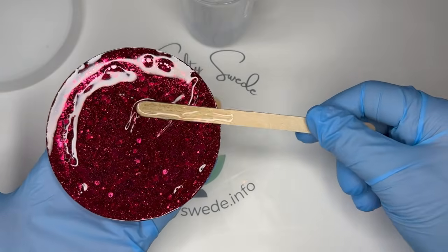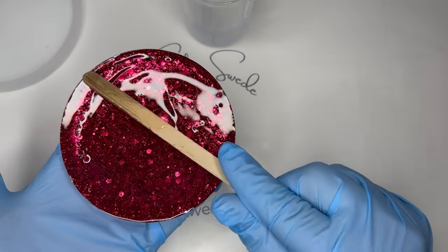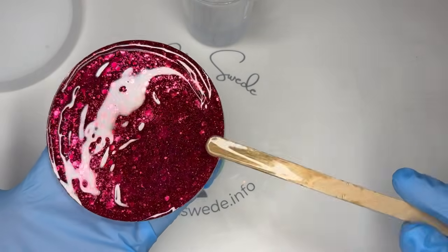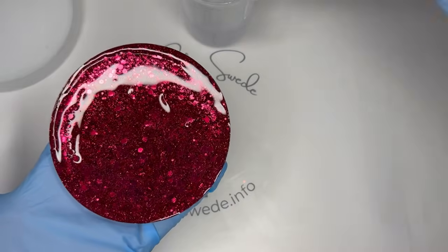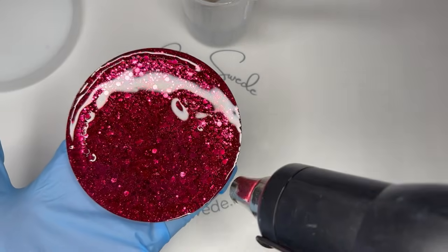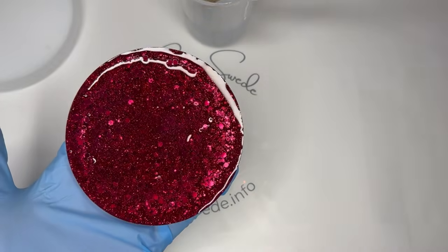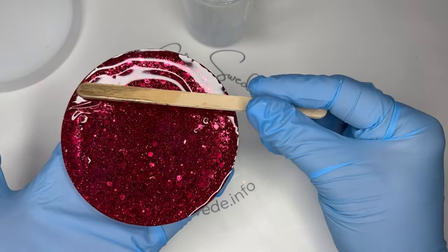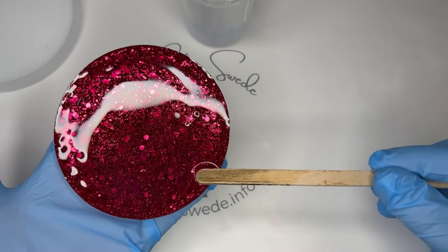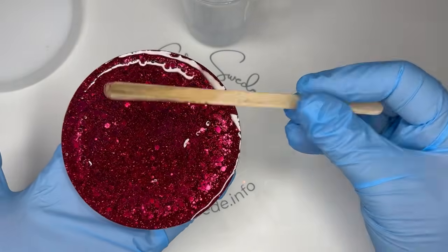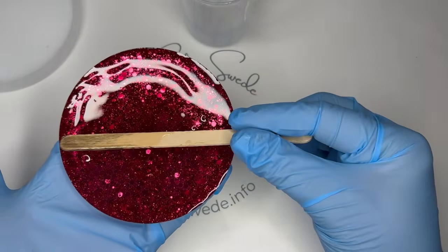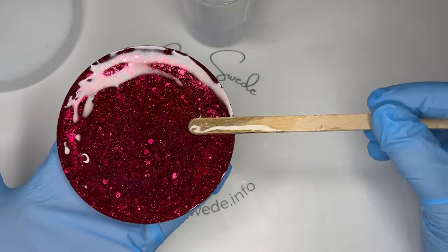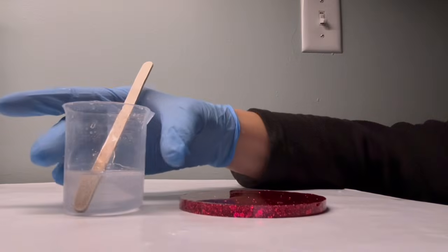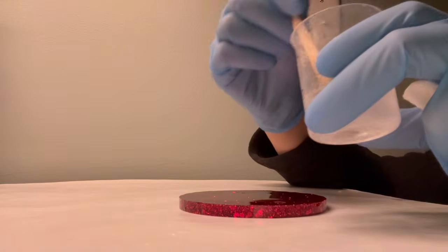Not all resins are suitable for top coating and doming. You just need to try it to find out if your resin will do what you want it to. In our case, the fisheye is caused by not enough resin. It's taking the path of least resistance, and if I keep adding more, the fisheyes will disappear, hopefully. By smearing the resin right up to the edge, I'm giving it a path to cover what I want. The lip is keeping it from getting too far, but you've got to keep adding very slowly so you don't overflow.